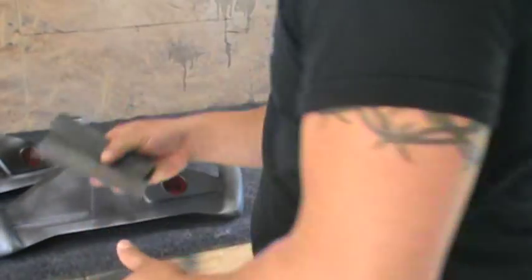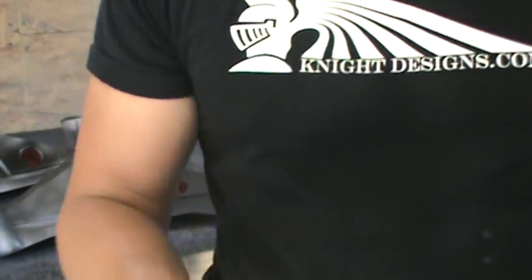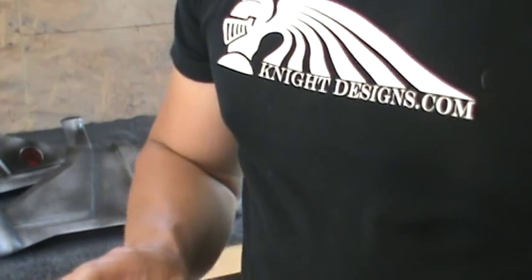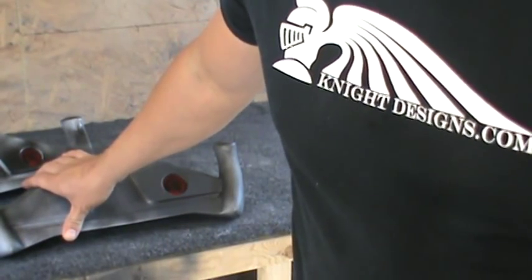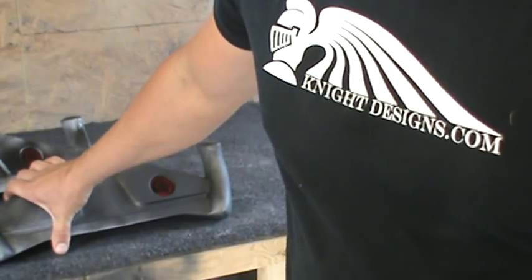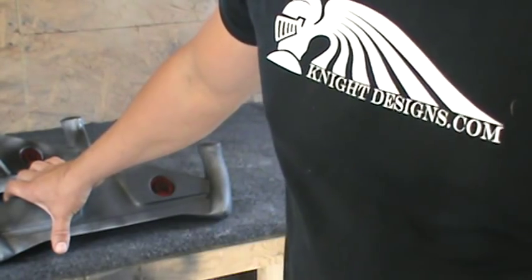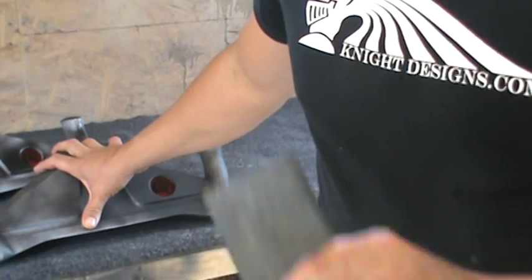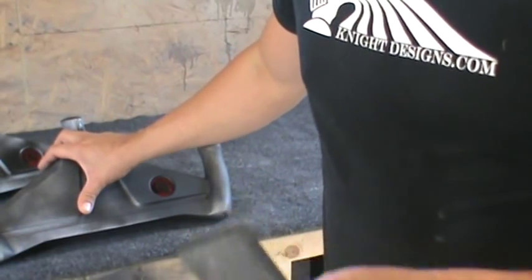Let me show you what goes on with blocking. When you get this wheel, best thing you can do is get you a rubber soft block. 3M makes these. You can get it at any body shop, any supply store. Now about this wheel, I've done all the prep work. So you are at the stage that's called ready for paint. So it is in primer, in guide coat. All you have to do is water sand or dry sand this wheel with any grit above 500. I use 500 to get ready for paint. Some people prefer 600, 700, 800, even 1,000. That's totally up to you.